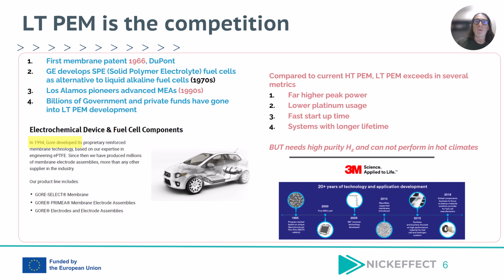So, in a way, you can think of it as stiff competition. If you compare what we can do today with our current materials to low temperature PEM, there are really some key metrics that are being exceeded by low temperature PEM that we, with our current product, have not been able to attain. Number one, far higher peak power, and probably this is the biggest difference. Number two, through these years of development and funding, lower platinum usage because it can start at lower temperature, very fast startup time, and typically longer lifetimes.